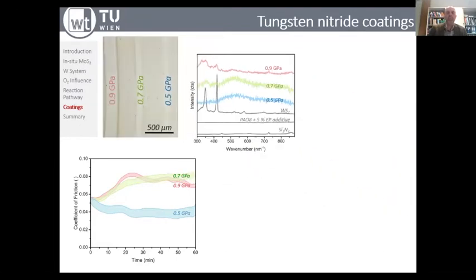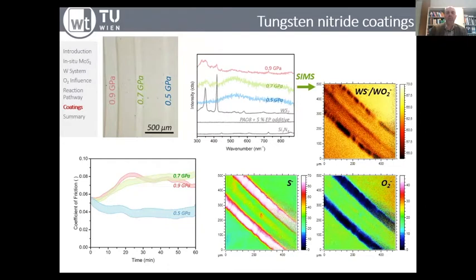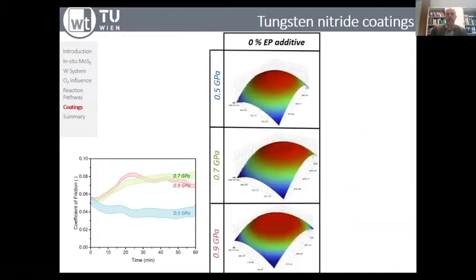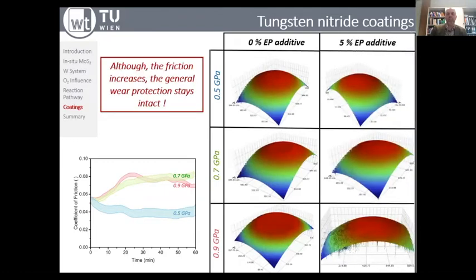And when you look a little bit more in detail into the wear tracks, we did some SIMS, secondary ion mass spectrometry, where you can even see that especially the side tracks of the wear patches are very much enriched in sulfur and depleted in oxygen. So oxygen is consumed by the system. Sulfur enrichment takes place, which again validates and proves the scenario of the tribofilm formation. This is one part that needs to be considered, of course, but if you go a little bit more ahead, you can also see clearly on the counter faces, no additive, severe flattening of the ball surface.